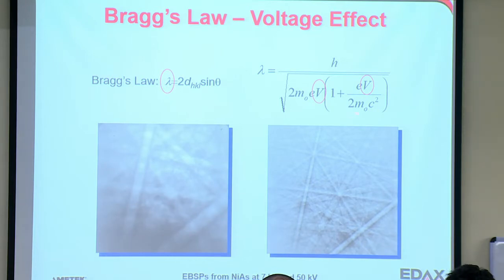And if you do that, then notice the voltage. This pattern's at 7 kV. This one's at 50 kV. And so you can see it's actually exactly the same pattern. This band here corresponds to that band there. This one is here. But the bands are much wider here. And that just has to do with this equation here and where these voltages come into play.